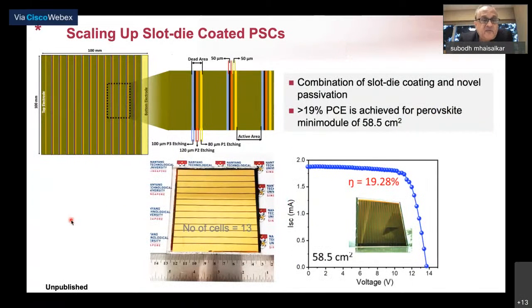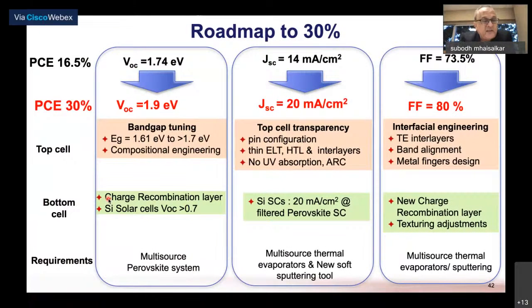Similar to what we've done with evaporated cells, we also worked on scaling up to mini modules. The mini module that I'm sharing with you is almost 60 centimeters square, and at 60 centimeters square, we can get efficiencies in excess of 19%. Similar to evaporated perovskites, you had to take care of etching for all three layers, and the proper design of each of these stripes is important, subsequently, from the perspective of tandem solar cells. So I actually did not include any tandem data so far.